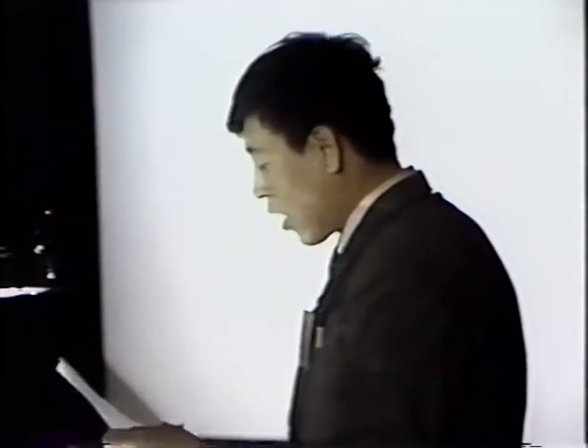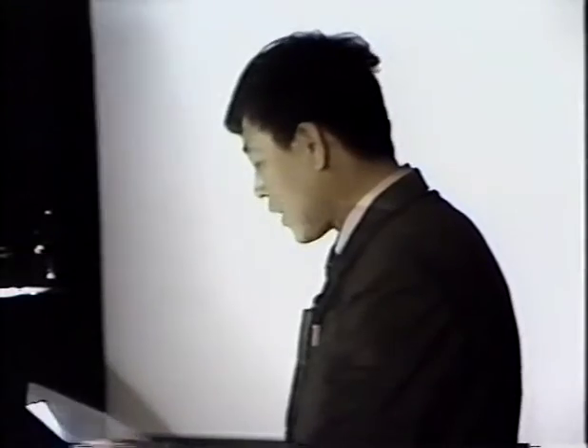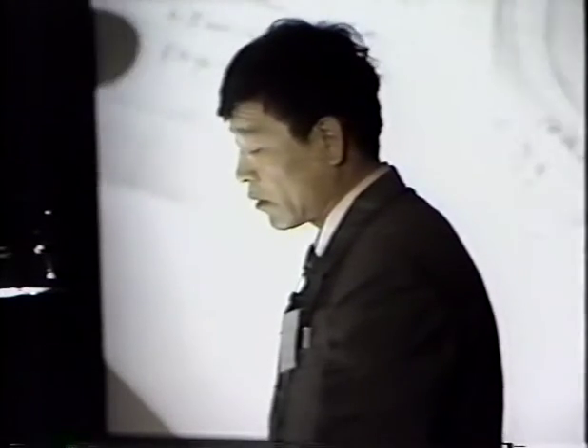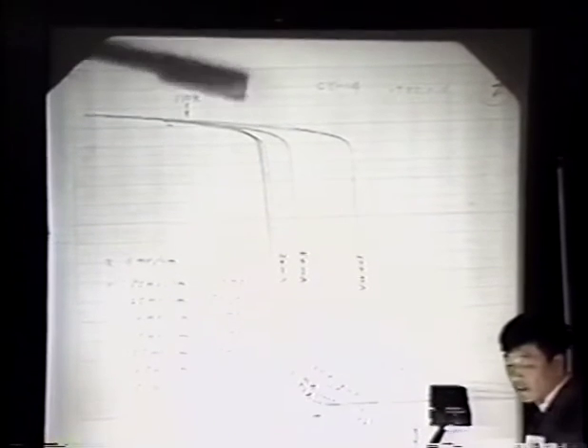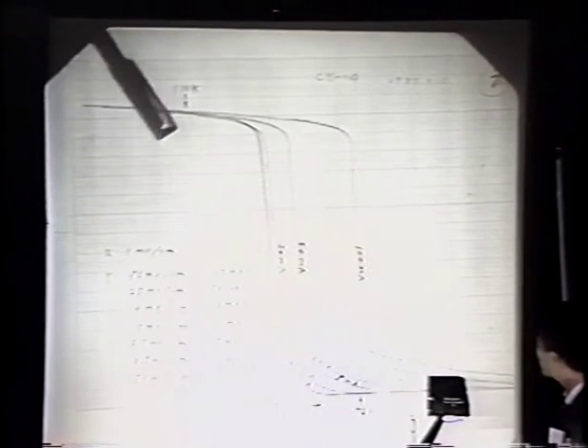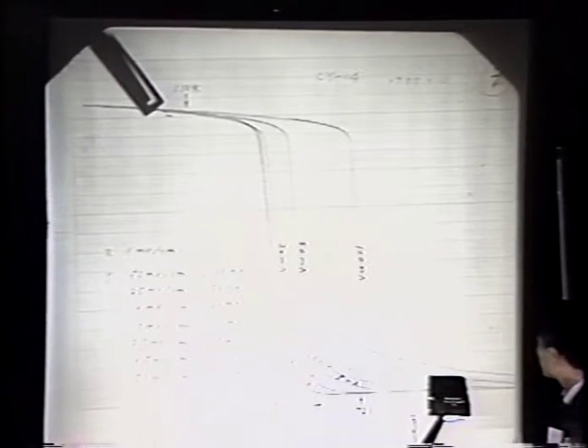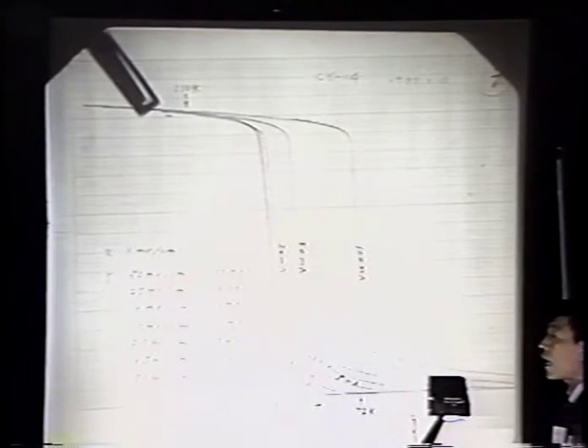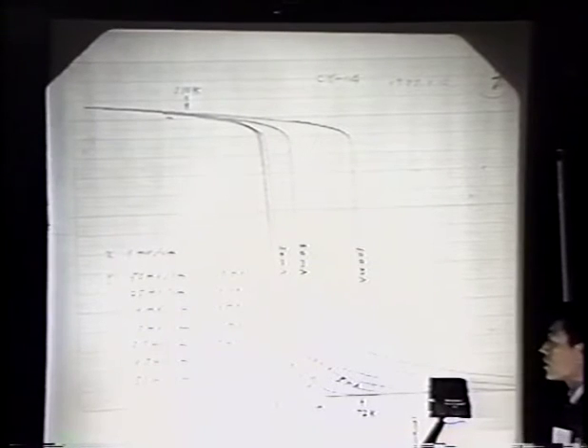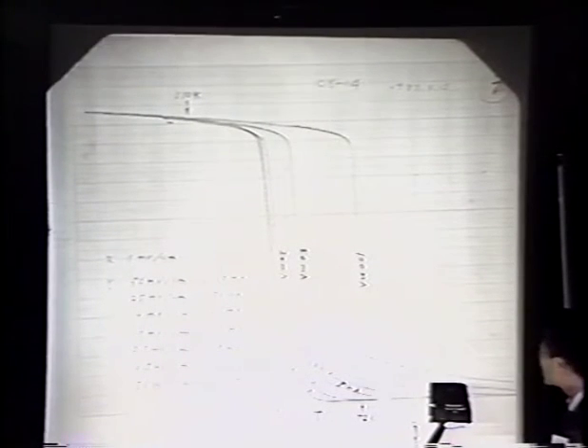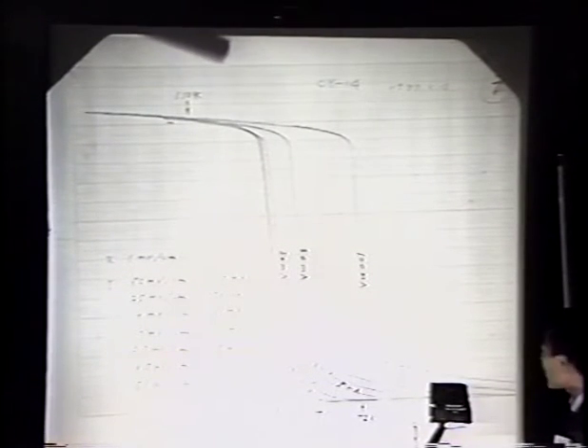How do we determine the onset of the TC? We use different currents to measure the resistivity transition. We can see that with the different currents, the deviation from the other curve at the onset is at 110. But I have to point out that this phenomenon is not only from the superconducting transition.